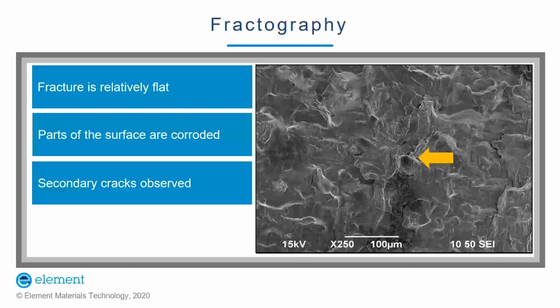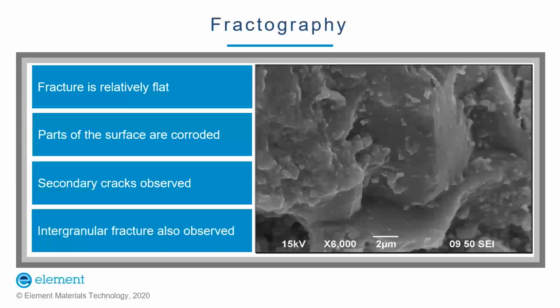Observation also showed a transgranular fracture surface, and we have also seen a secondary fracture crack. Some locations of the fracture surface under high magnification showed intergranular fracture. So it can be concluded that the tube went through a mixture of failure modes, which is transgranular and intergranular fracture mode.